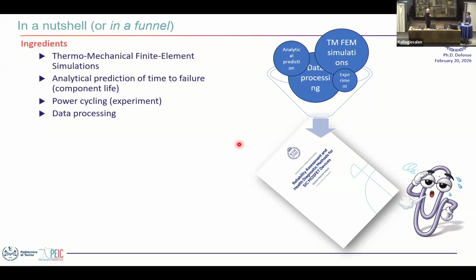But I didn't want to just say it without experimental validation, because I didn't have it. It would be good to validate by testing which layer will fail. Otherwise, I feel it's the die-attach solder DA bottom, underneath the die, that will fail because of high viscoplastic dissipation density, and in the case of molybdenum, where it's the highest, molybdenum is worse. Okay, so it's still too early to say something. I will say that one. Yeah. Okay, I see.